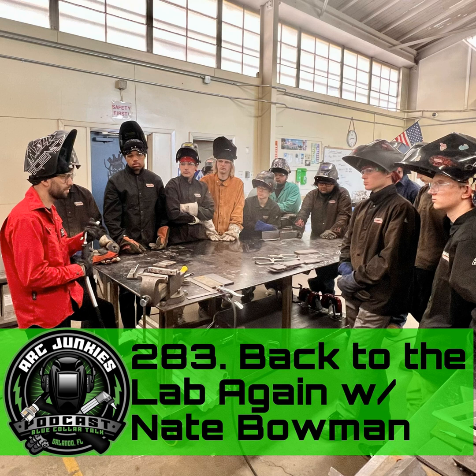Hey, have you considered spray transfer? Because if I lock you in at 250 inches a minute with a short circuit, this is going to be good for 1/8-inch material, but beyond that, this is not going to work for everything. Yeah. Could you pass a vertical 1-inch plate on short circuit? Yeah, probably, if you tried really hard and preheat it, maybe, but the reality of trying to weld on that stuff, like we were saying, is it's slow. There's a better way to do it.